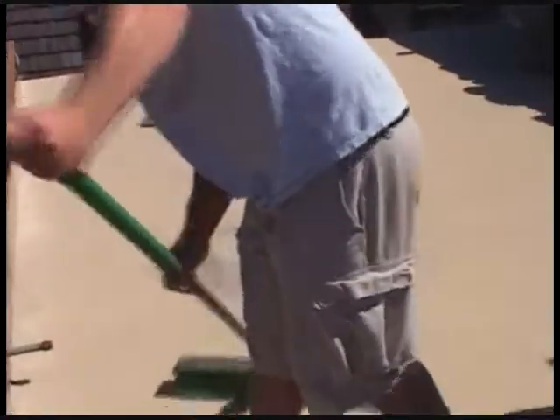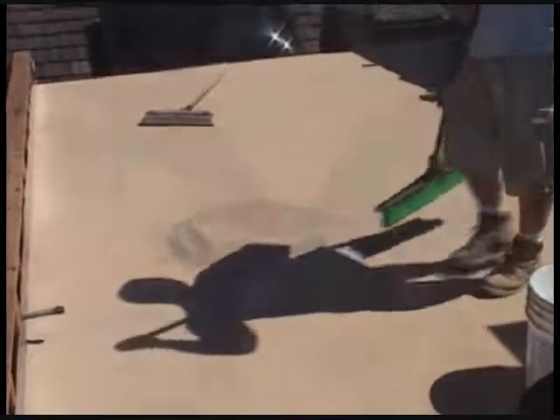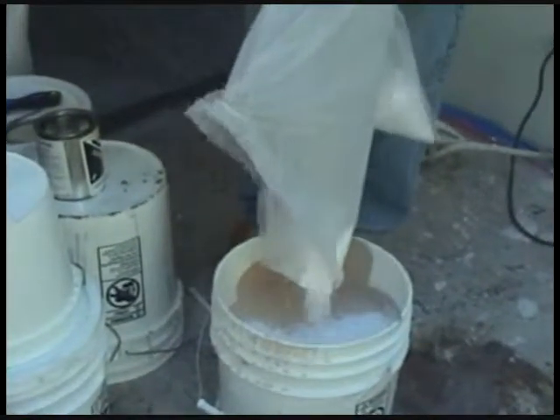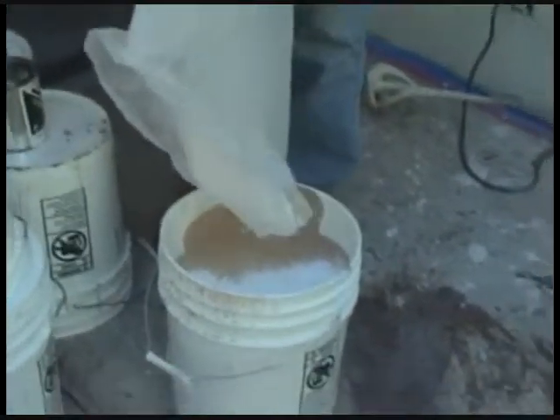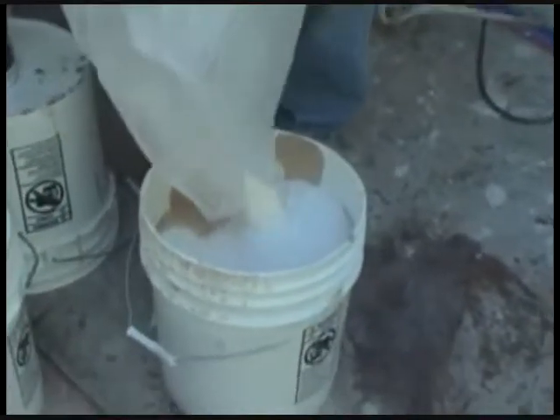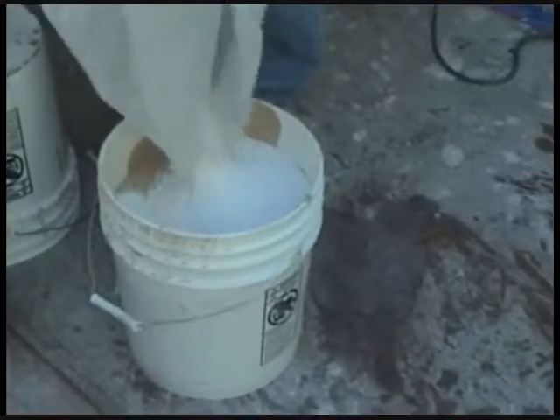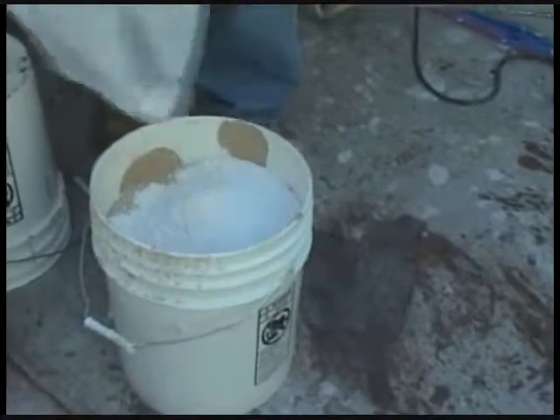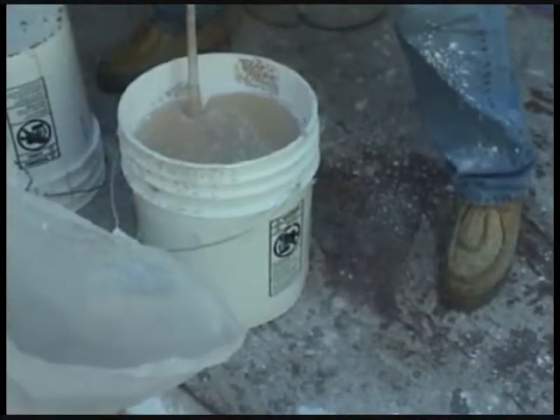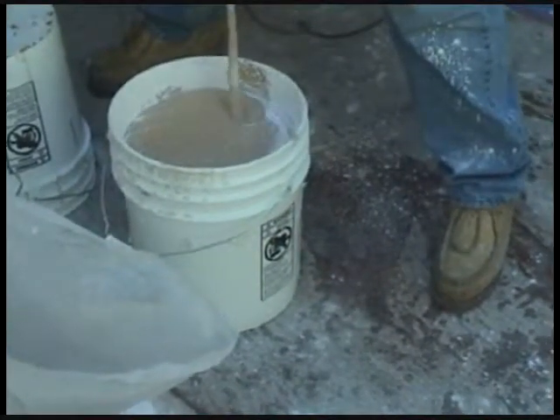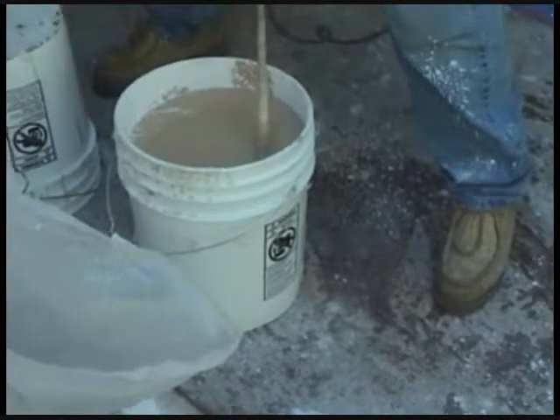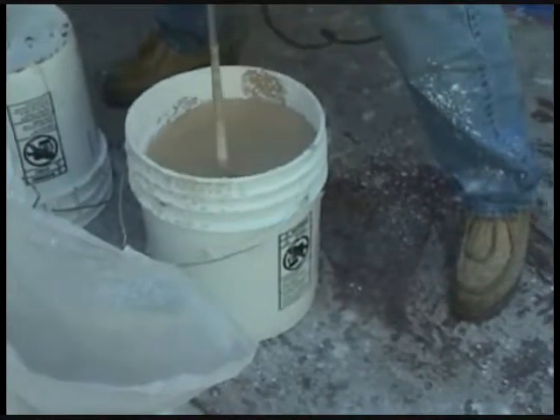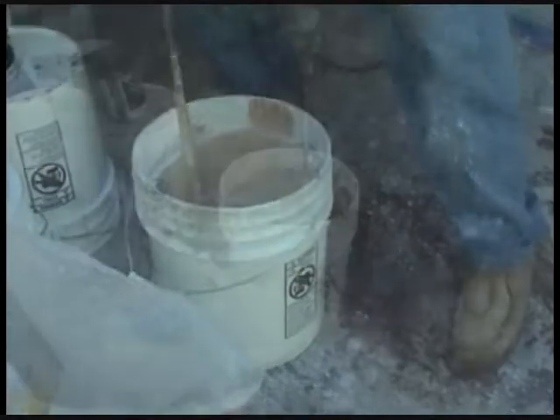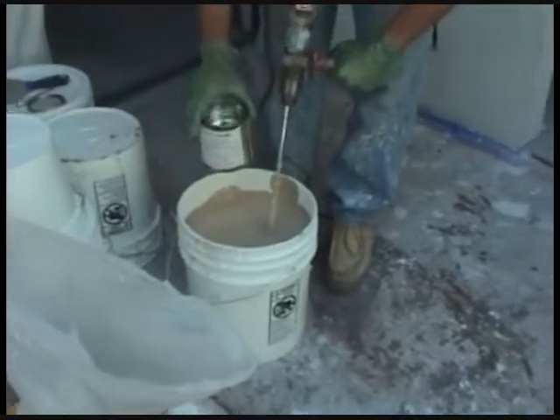Afterwards, in about 2 hours, or between an hour and 2 hours, the contractor sweeps off the excess sand and removes the sand and begins the top coat mixing. The top coat, in this case, is a fire retardant top coat, and he adds the fire retardant powder to the coating. He mixes it together and then adds an accelerator to the coating.